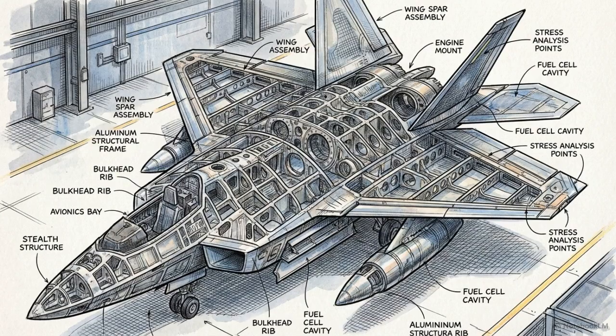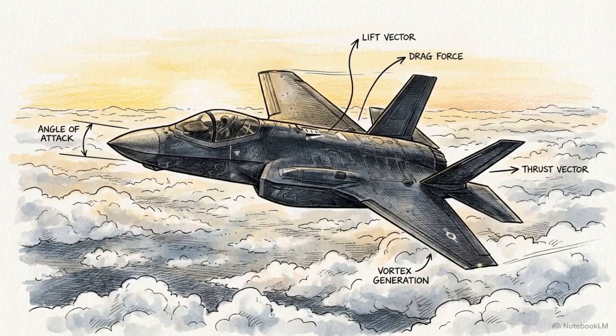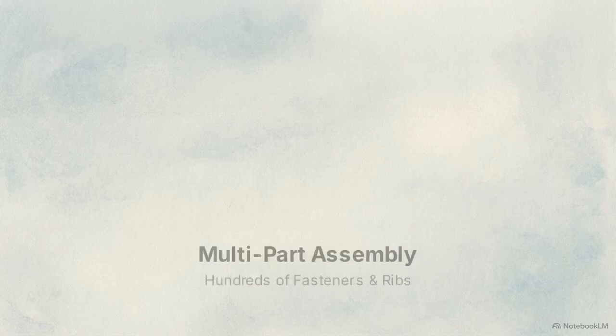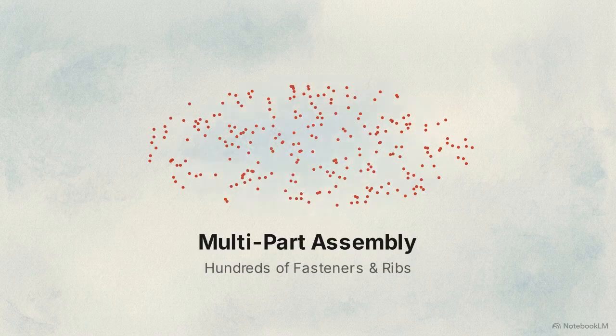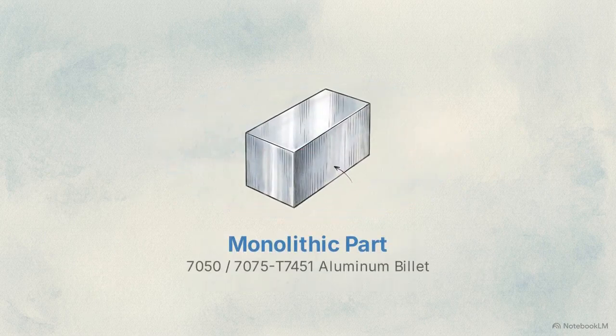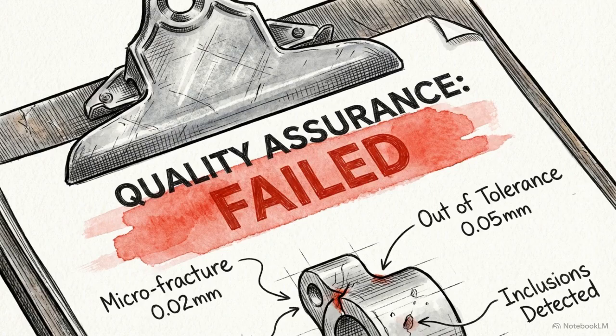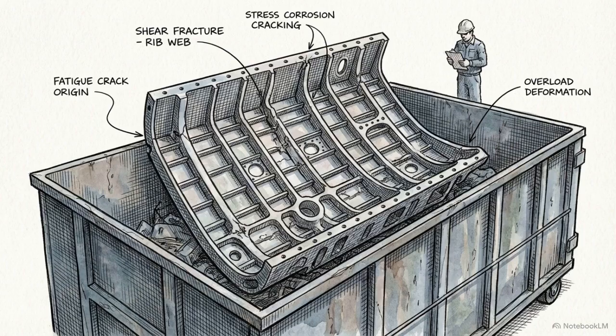The F-35 Lightning II bulkhead relies on this process. The F-35 is a supersonic, multi-role stealth fighter developed for global defense fleets. It uses monolithic parts, where a single aluminum piece replaces hundreds of individual fasteners and ribs. The financial risk attached to these parts is severe. A single stress fracture or tool breakage caused by improper cooling can force an inspector to scrap a part worth over $100,000. At this scale, fluid application is the primary vector for catastrophic structural risk.